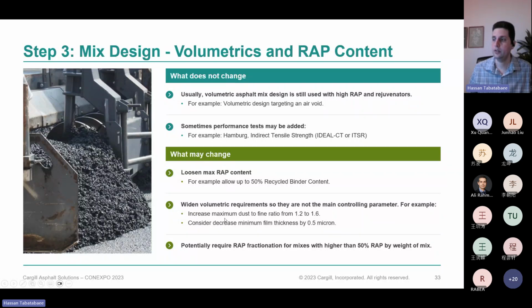If a specification has a dust to binder ratio, that is a ratio of the passing number 200 mesh, the 75 micron mesh, to the binder content, that requirement might need to be modified because usually recycled RAP will have more dust on it, so it'll be hard to meet these. And that also means the average film thickness of bitumen on the aggregate might decrease. So if a specification has film thickness requirements, those will need to be modified.